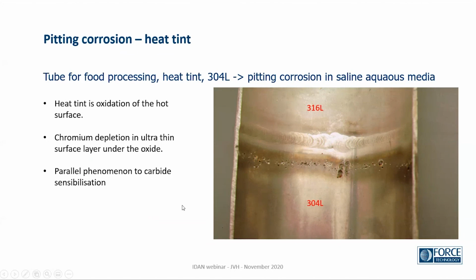Pitting is, in this instance, related to oxidation. Oxidation along the weld. This is the internal side, the root side, and purging with gas has been attempted, but it has not been fully efficient. So we have pitting formation in this discolored zone, oxidized zone along the weld root. The reason why it's so extensive on this side is that it is 304 and this is 316. So if this was also 304, we would have expected this area to be attacked as well. The reason for difference between the two sides is probably that we have had the purged gas coming from the top and being heated over the weld, so that the reaction is faster on this side.